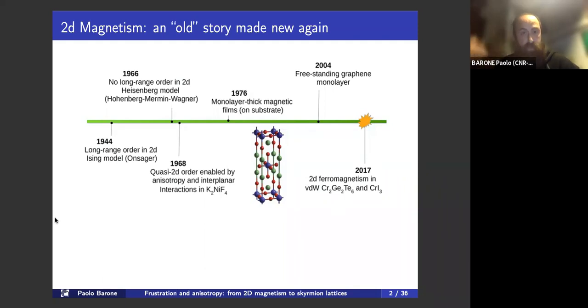Anyhow, one had to wait 20 years more or less before Mermin and Wagner, developing on the work that Pierre Hohenberg was doing on the long-range order in two-dimensional superfluids and superconductors, proposed a theorem which showed that no long-range order could be established in 2 dimensions. Nevertheless, a couple of years later, thanks to advances in neutron scattering technologies, experimentalists were able to observe and to characterize a kind of quasi-2-dimensional order in bulk systems.